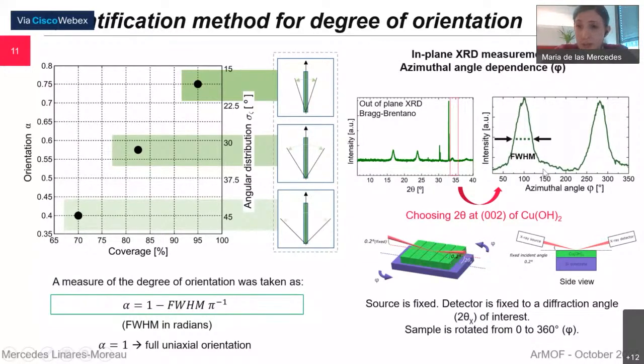But if you have a profile that looks like this, with peaks separated by 180 degrees because of the symmetry, this means that there is a preferential orientation in the sample. The sharper these peaks are, the more oriented the sample is. So what we want is to get the sharpest distribution that we can. We used the full width at half maximum to quantify this, and we use a normalization of this parameter that we call alpha, which has a value of 1 when we have full uniaxial orientation.